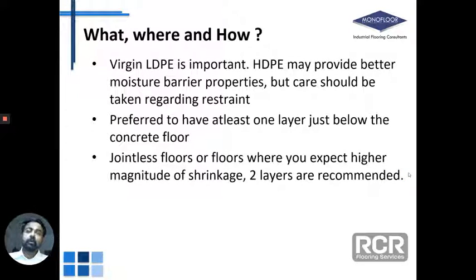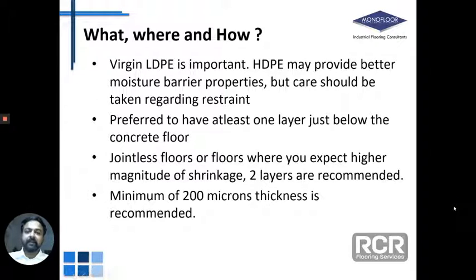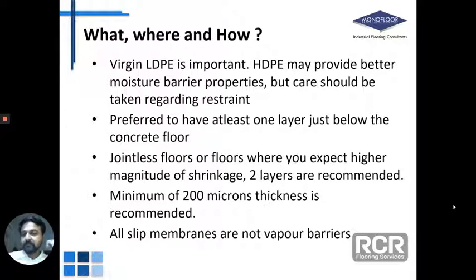And when you go for a jointless floor or any floor that is expected to have a high amount of shrinkage, you typically like to have at least one layer or maybe even two layers of slip membrane. Preferably, the usual typical specification is about 200 microns of LDPE sheet used as a slip membrane. All slip membranes are not vapor barriers. Vapor barriers are to be specified using the specific property that is achieved using LDPE, using HDPE, or the performance properties that are usually specified for vapor barriers. The bottom line is all slip membranes are not vapor barriers.